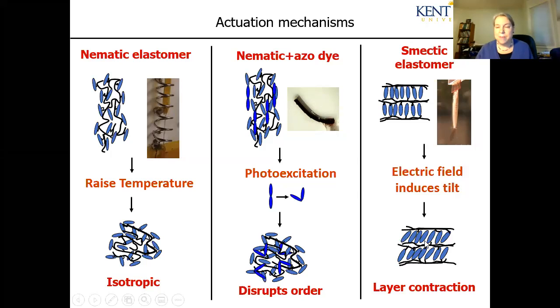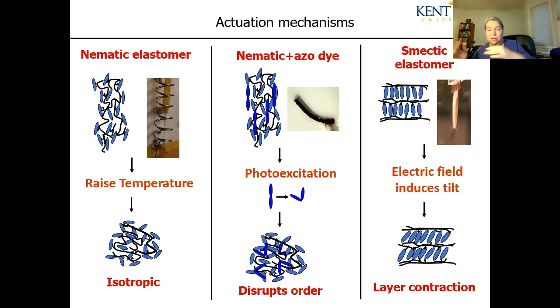In the case of the smectic phase, as I mentioned, it is a layered phase, and it's a chiral material. When you impose an electric field transverse to the layers, it makes the layers tilt. And like the books on a bookshelf at the library, if they all tilt over, you get a change in the layer spacing, and this causes a mechanical contraction. You would think the whole sample as a result would just shrink and maybe shear a little bit. Because it's not completely flat and because there's a little asymmetry between the front and back of the sample, it does also make it twist.